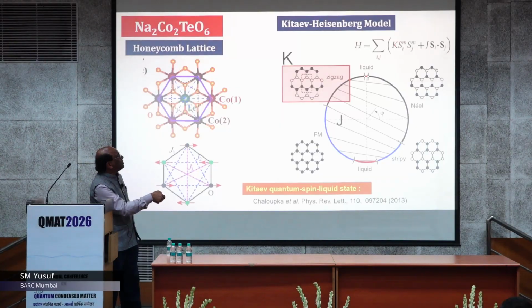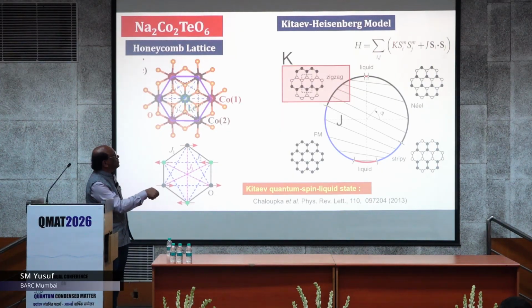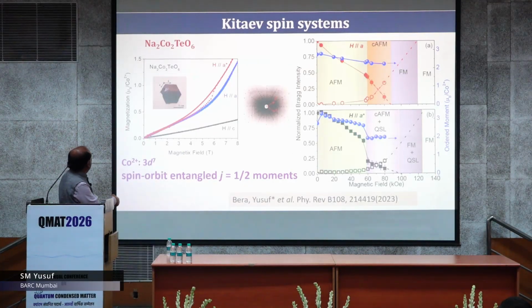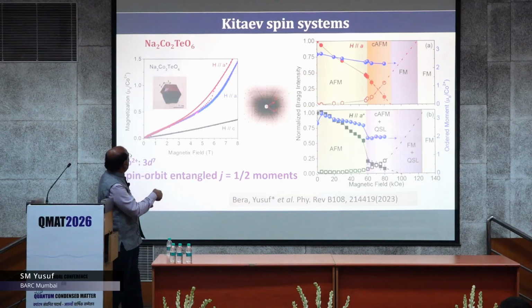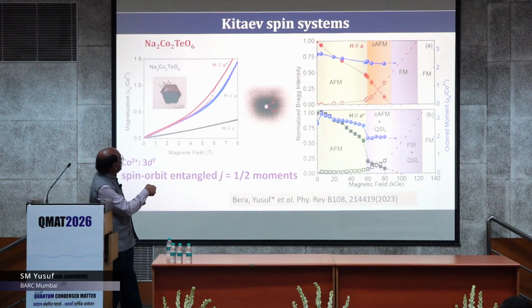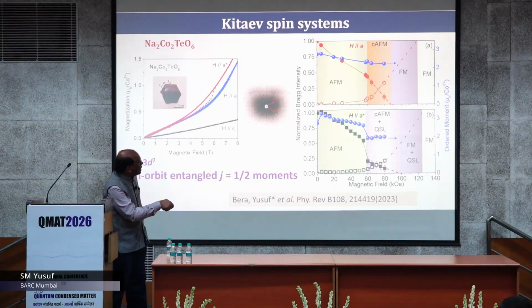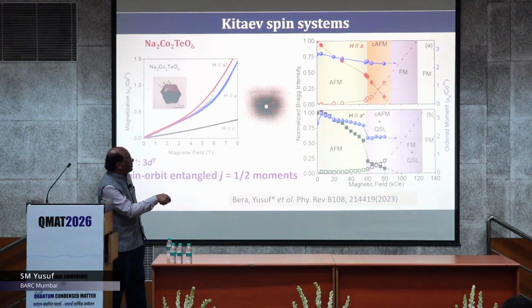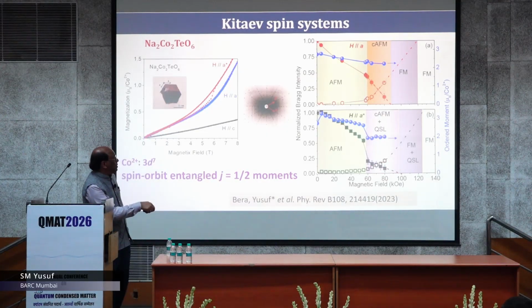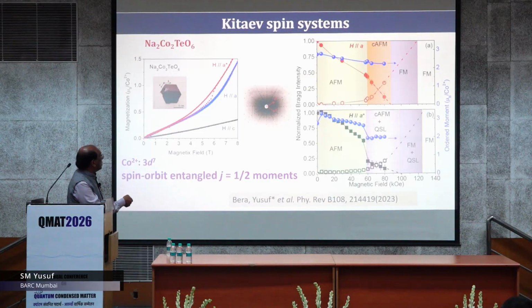If it is purely Kitaev, then J is not there. See, this is the theory developed with respect to mixed Heisenberg and Kitaev combination, and our system falls in this domain. So there is a finite Kitaev term. And in this case, by doing magnetization on a single crystal along different field directions, when the field is H parallel to a star, we could see the quantum spin liquid coexisting with the canted antiferromagnetic state over this field range. So this kind of phase diagram came out by doing this kind of study.